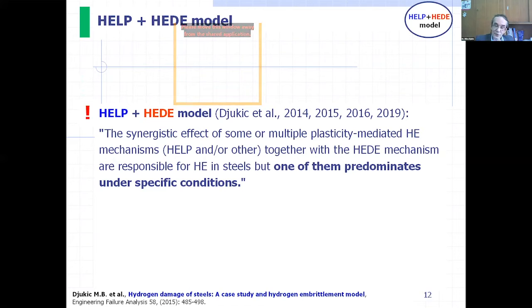So here is the definition from 2014, which we further developed in 2015, 2016, and 2019. The HELP plus HEDE model: the synergistic effect of some or multiple plasticity-mediated hydrogen embrittlement mechanisms, HELP or others, together with the HEDE mechanism, are responsible for hydrogen embrittlement in steels, but one of them predominates under specific conditions. So you can see here the difference from the HELP-mediated decohesion model, which stated that the major mechanism always active is the HELP mechanism, and that an initial activity of HELP is always a prerequisite for the eventual activation of the HEDE model. So that's the HELP-mediated decohesion model, while contrary, the HELP plus HEDE model indicates that almost simultaneously these two hydrogen embrittlement mechanisms are operative.